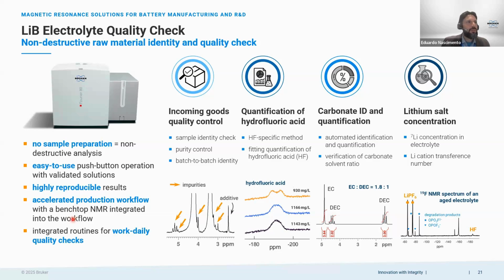And we have also thought about how you can guarantee that the system is performing well. So we have some quality checks that are automatically included in the workflow routines. And then you can use, for example, this report to check the incoming goods, like when you receive your electrolyte from your electrolyte supplier, you check to see the quality. We saw that many times from companies that were saying, I will not do HF analysis in this electrolyte because we know that this is quite fresh. But then they open the bottle, they do the analysis, and they see a huge peak there. And then you cannot 100% rely on the quality of the electrolyte for many reasons. So with this method, you can do this sample identity check, or even when you talk about batch-to-batch identity.